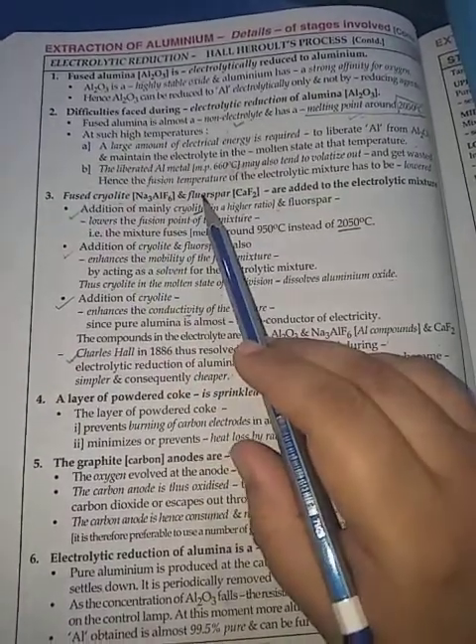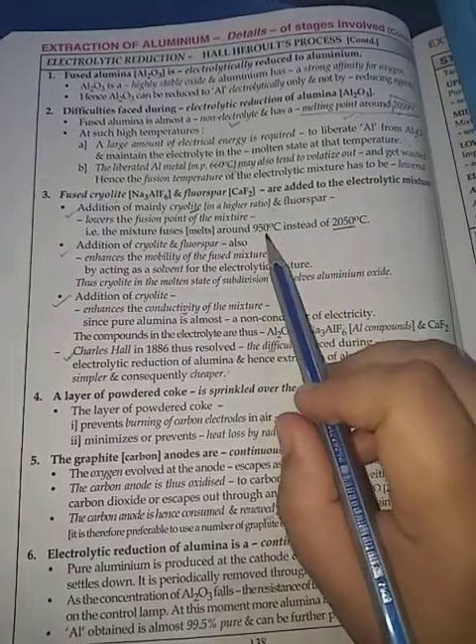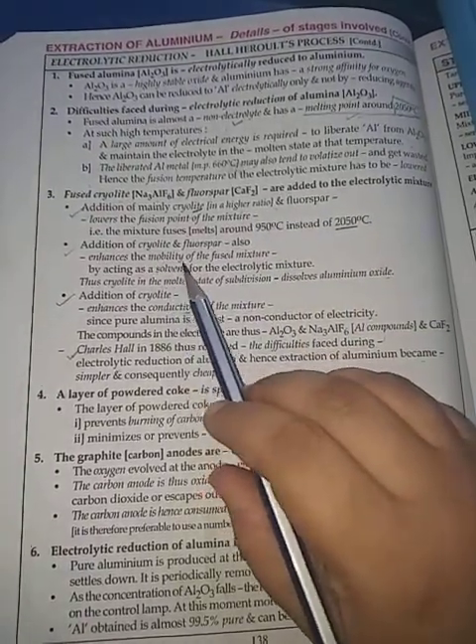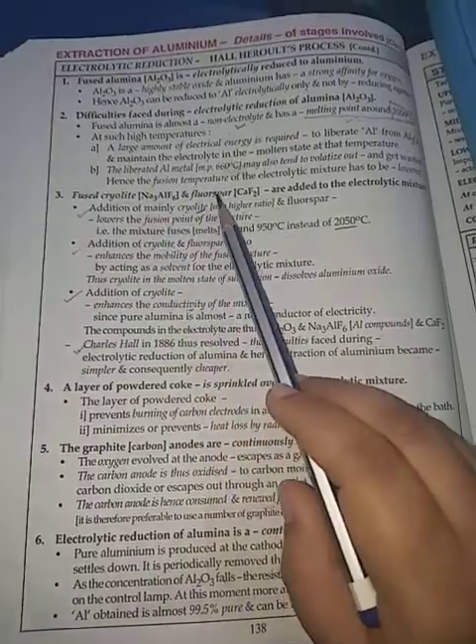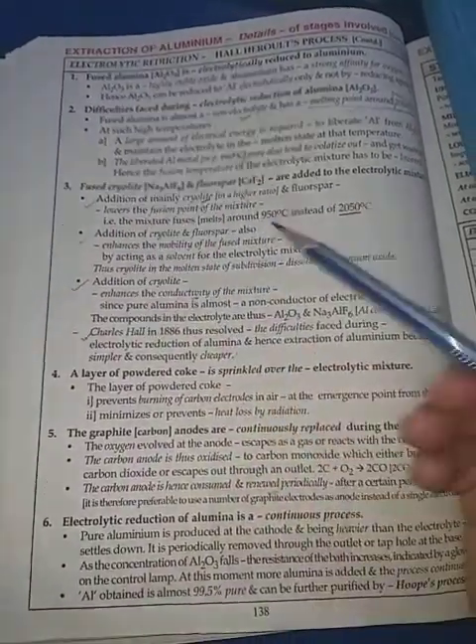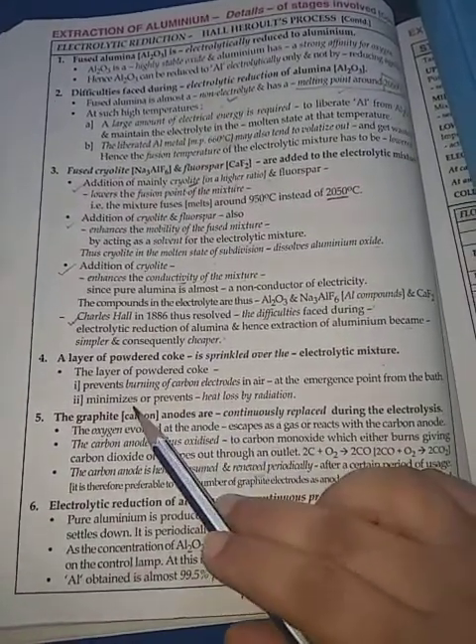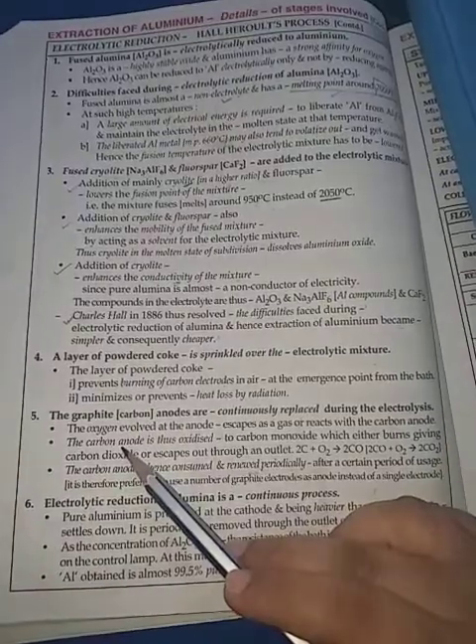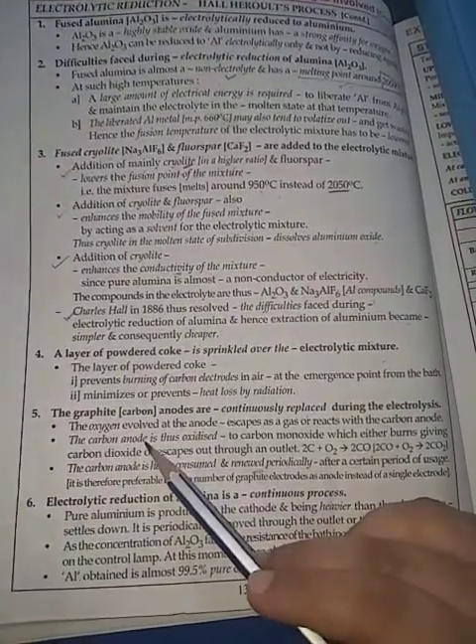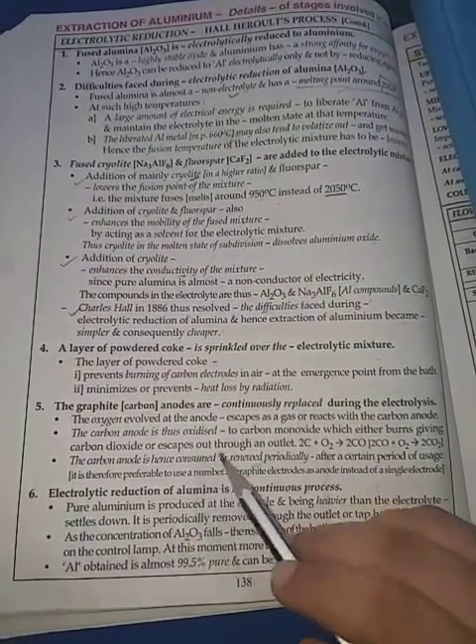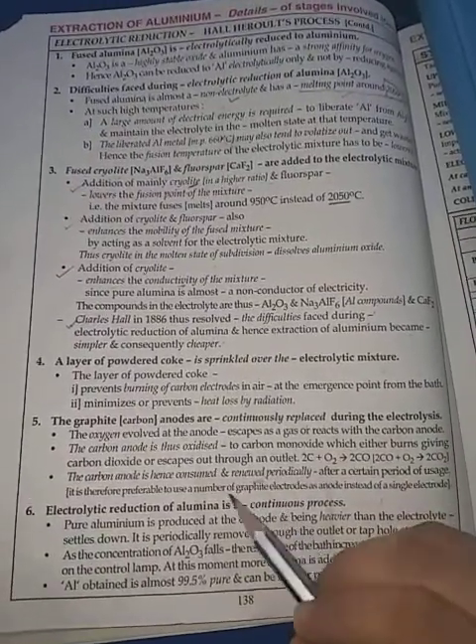This cryolite and fluorspar reduce the melting point from 2050 to 950 degrees Celsius only, and they also enhance the mobility of the fused mixture. So two things are done by these, and it is a very important role of these two in the process. Now a layer of powdered coke is added which prevents the burning of the carbon electrode, and it also minimizes or prevents the heat loss by radiation. A number of carbon anodes are used because these anodes keep on reacting with oxygen to form carbon monoxide and carbon dioxide gas, and they will be consumed very readily. So a number of carbon anodes are used.